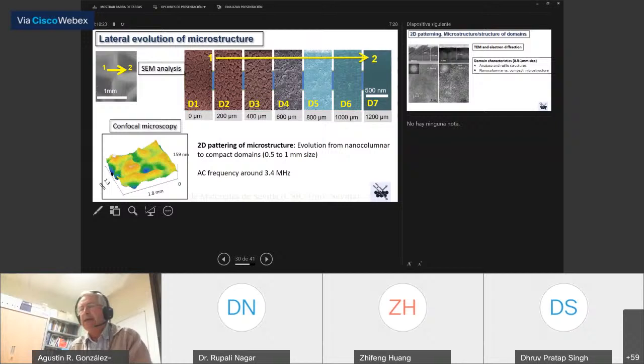If we look at the microstructure with electron beam microscopy, what we can see is that we move from this area to this area. We are moving from an area where we have the typical nanocolumnar growth of titanium dioxide to another area where we have a compact nanostructure. Looking by confocal microscopy, we have this typical structure where we have some valleys and hills, with a difference in height of circa 100 nanometers for films which are 300 to 400 nanometers of average thickness.